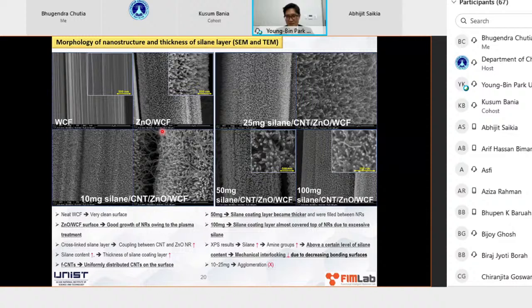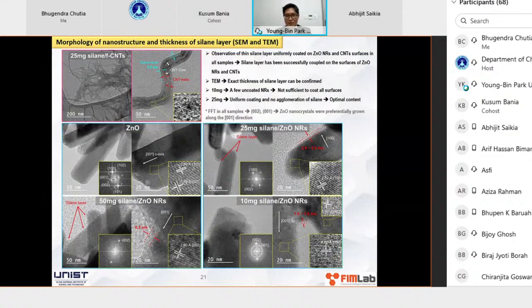So based on this visual or microscopic analysis, we optimized that the best silane condition was by dip coating the carbon fiber with the silane in the range of 10 to 25 milligrams. Okay. And TEM results also showed the thickness. So here we're trying to exactly measure the thickness of the coated layer, the silane layer here.